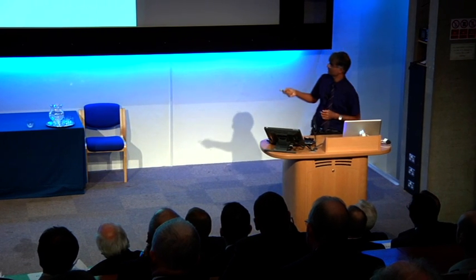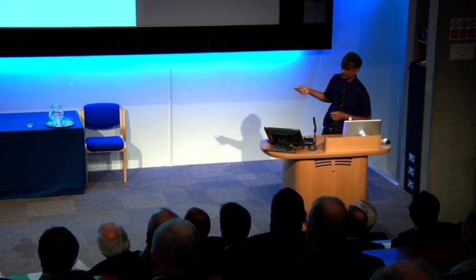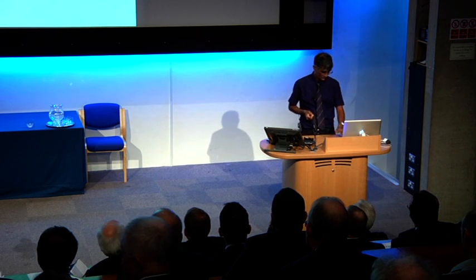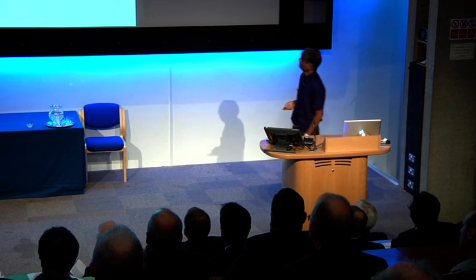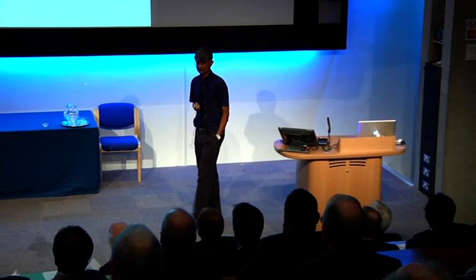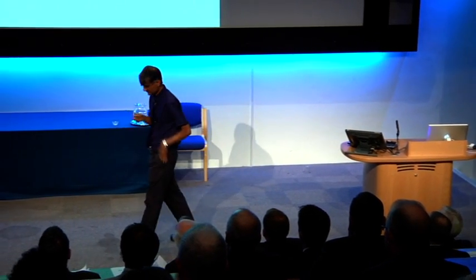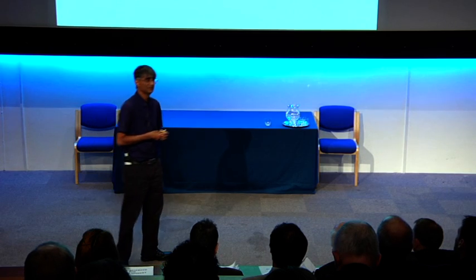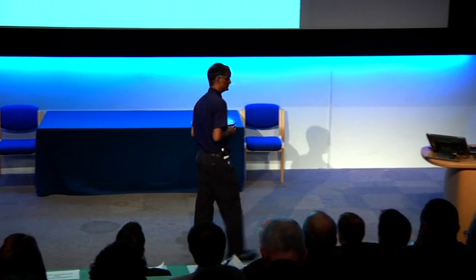I'm also going to describe some of Pedro's work here, and this is work that I want to do, neural networks. So the original work comes from Weibull statistics. Weibull statistics were developed to deal with brittle solids. If you make a brittle solid larger, then it cracks at a smaller stress, simply because the probability of finding a defect becomes higher in a larger object. And that is why you can bend a glass fiber, but you can't bend a chunk of glass without breaking it.